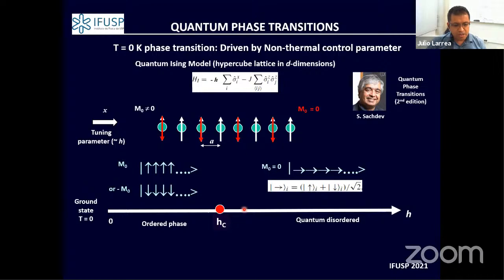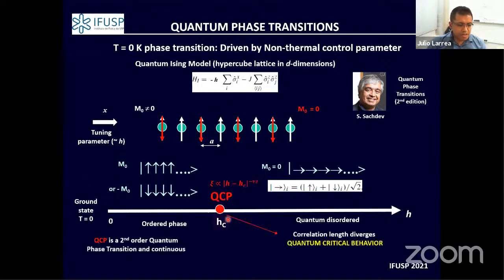And the situation you observed is that at zero temperature, you pass from one ordered phase to a quantum disordered phase, crossing a quantum phase transition at some critical value. In order to know if this transition is continuous or discontinuous, you go to a deeper investigation of this Hamiltonian, and what you observe is that the transition is, in fact, continuous.